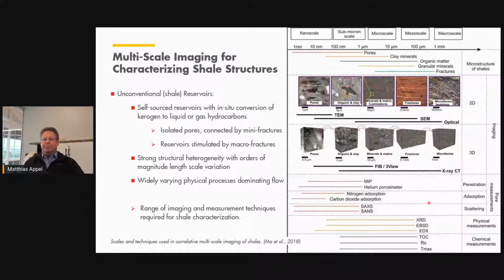We have seen that really popping up when we worked a couple of years ago a lot on unconventionals. Again, I don't want to repeat the entire plot here, which shows the same, that different length scales in unconventional reservoirs, so basically the self-sourced shales, require very different measurements. But I just want to point out that because of these very strong structural heterogeneities, the industry actually has made mistakes by believing that one can work with the conventional imaging techniques like medical CT scanning, maybe SEM, to describe the entire pore structure of unconventionals and predict the flow performance in unconventionals. That went very badly. A lot of basically uninterpretable measurements have been made, or wrong modeling results have been obtained. So different length scales have their own physics, have their own structural information, and we need to have the adequate measurement technique and modeling technique to describe these.